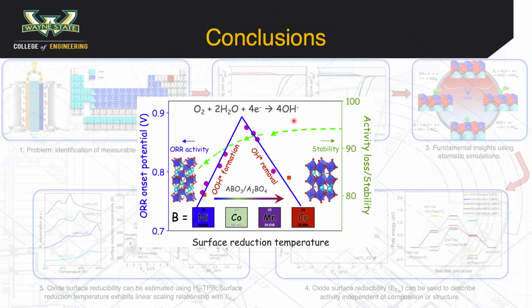The value of this work is twofold. What I mean by that is such activity descriptors can be extended to other catalytic reactions, such as high temperature CO2 electrolysis using these mixed metal oxides, as well as high temperature oxygen reduction and evolution reactions in solid oxide fuel cells and solid oxide electrolyzer cells. The volcano would hold good. The only thing that would change is the optimal composition close to the top would shift based on the temperature of interest.